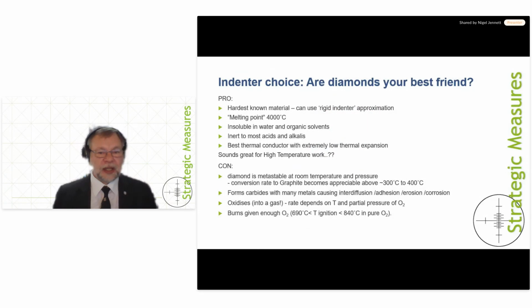But unfortunately, diamond is a metastable material, and it starts turning to graphite, and that gets faster and faster with higher temperatures. And by the time you get to 300 or 400 degrees Celsius, it's a big problem. Now, it also forms carbides, and so you can cold weld to your sample, or you can wear away your tip, or you can damage your sample. And of course, it oxidizes, and you have the potential of making an extremely expensive contribution to global warming by creating carbon dioxide by burning your tip.